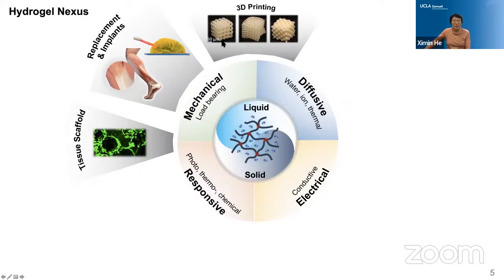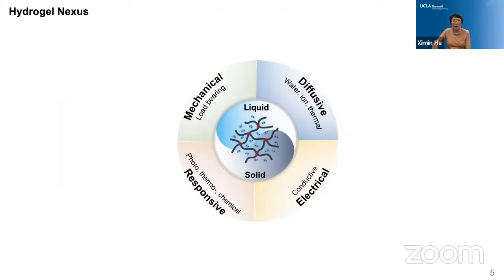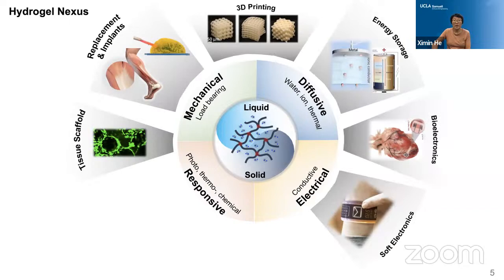And despite this porous structure, the mass transport or liquid diffusion through this porous network may not be that perfect yet. Therefore, tuning the pore structure to enable faster fluid transport through the network can benefit, for example, ionic conductivity, which can enable the application in maybe energy storage, like in battery.